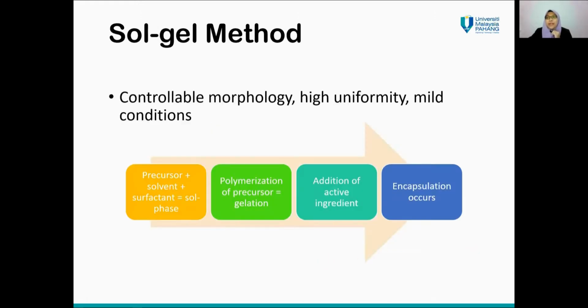Okay, now we move on to the sol-gel method. Sol-gel method is a widely used physicochemical process to fabricate nanocapsules by metal oxide with controllable morphology and high uniformity to load active ingredient in very mild conditions. In a typical sol-gel process, there are 4 processes involved, including combination of metal oxide precursor, solvent, and surfactant to form aqueous droplet known as sol phase. Next, polymerization of the precursor to build oxide cage, known as gelation. Next is addition of active ingredient. And lastly, the encapsulation occurs around the active molecule.